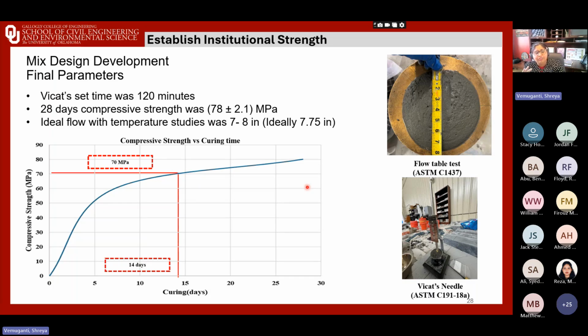And ideal flow, when we say ideal, with temperature studies in mind, we always shoot for a 7.75 inch flow table measurement. 7 to 8 inch is the range we've established, but in our prints, we always target the 7.75 inches. So by systematically connecting all these fresh state properties with print outcomes, we've established these final parameters that we always use till now during the printing process.